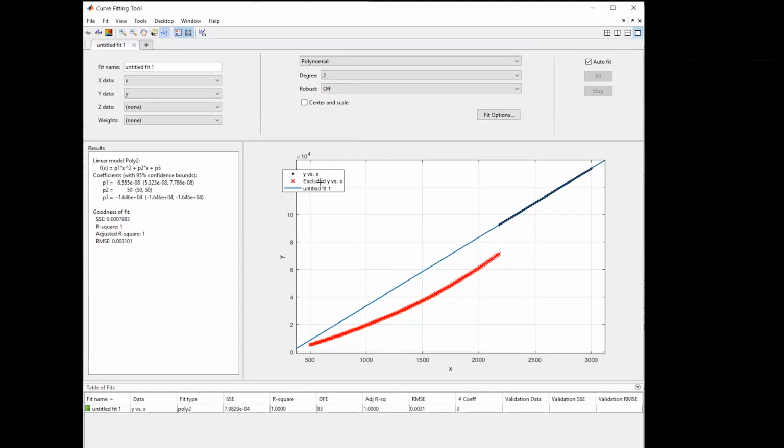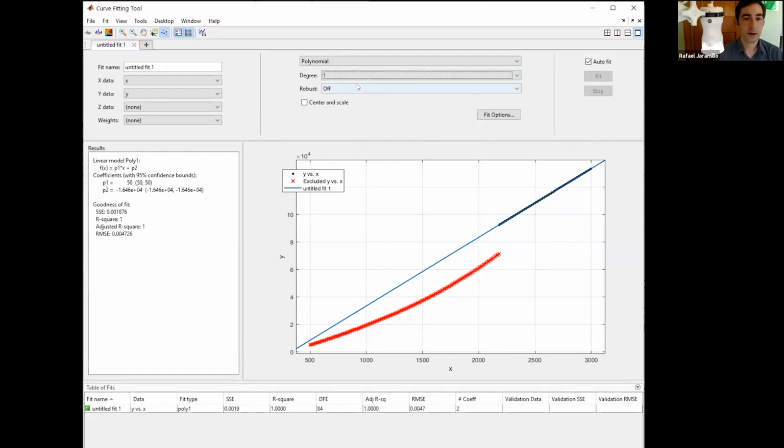Yeah, this looks like the quadratic term is really superfluous here. The quadratic term is really not needed. And if you can actually see this in the fitting results, in the value assumed for the quadratic term, which is close to 0, and the uncertainty in the quadratic term, which is large. So I think that the liquid phase in this particular material is better fit to enthalpy versus temperature being a straight line. And what is the slope of that line, by the way? What's the slope of enthalpy versus temperature?